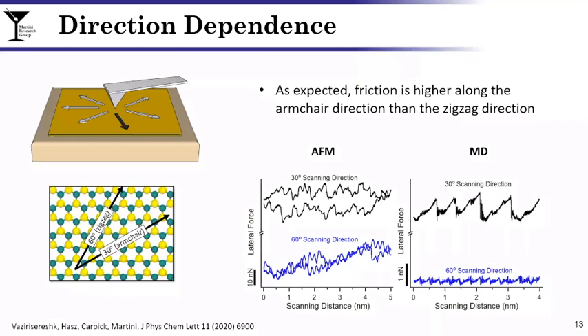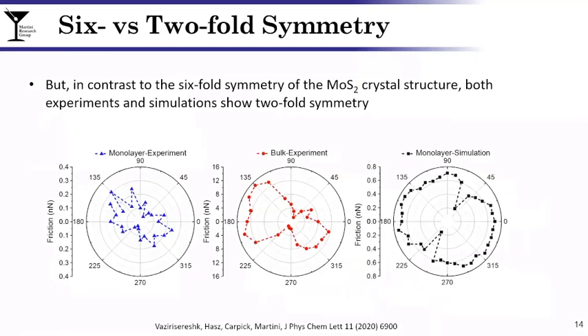In one, you have to overcome more, we'll say, atomic obstacles, meaning there should be higher friction. Shown on the right are two representative results from the AFM experiments and the molecular dynamic simulations. And you can see that in one of the scanning directions, we have very high friction, and in the other scanning direction, we have very low friction, reflecting the underlying atomic lattice of the MoS2. We repeated this experiment in all of the different possible sliding directions. What we were expecting is that we would have 6 low friction directions based on the 6-fold symmetry of the MoS2 crystal structure. But instead, in both experiments and simulations, and on both bulk and monolayer MoS2, we saw only 2 low friction directions.